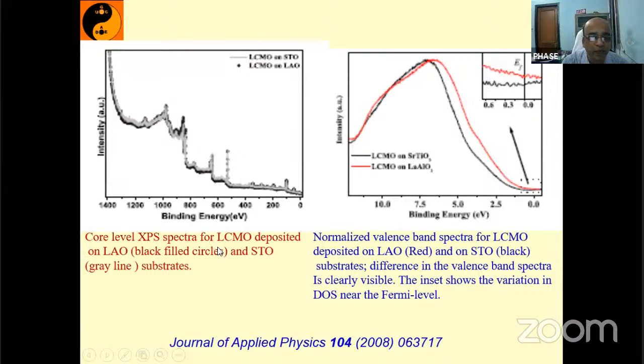You will see that this one LCMO is deposited simultaneously on the two substrates. One is the LAO substrate, lanthanum aluminate, and one is the strontium titanate substrate. You will see that the core level structure is exactly identical. Then one can conclude from this core level spectroscopy of XPS that both the films are basically having the same property. But if you go to the synchrotron-based valence band spectroscopy, you will see that both the spectrums are not the same. The LCMO on SrTiO3 and LCMO on LAO are also different.